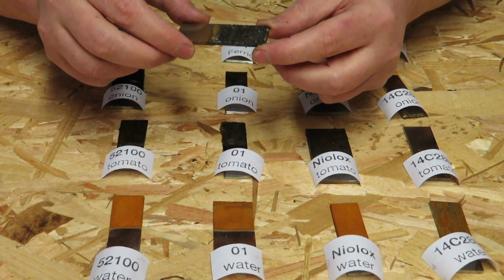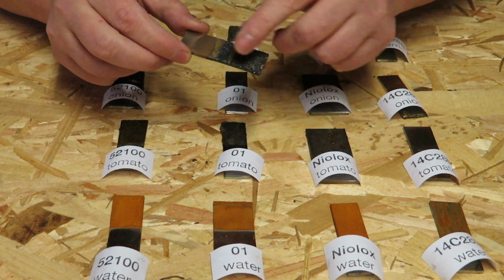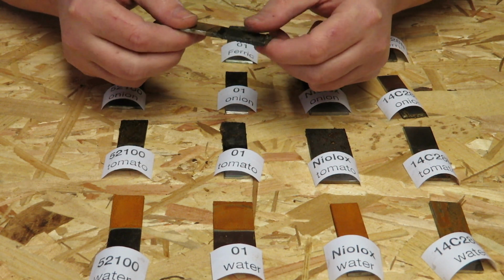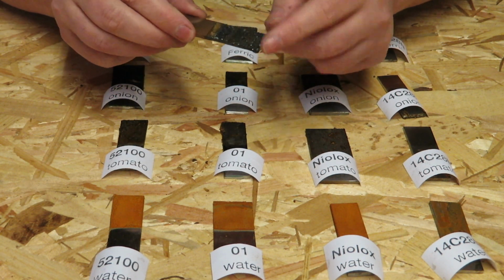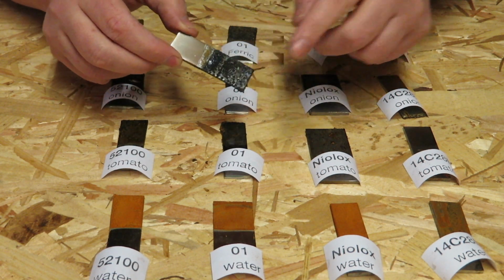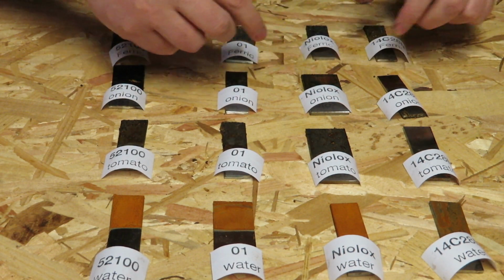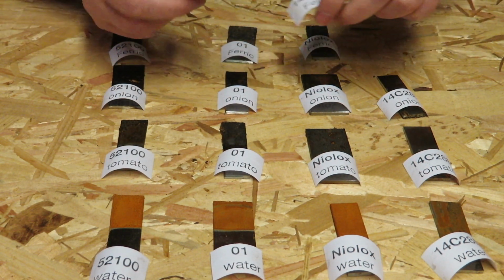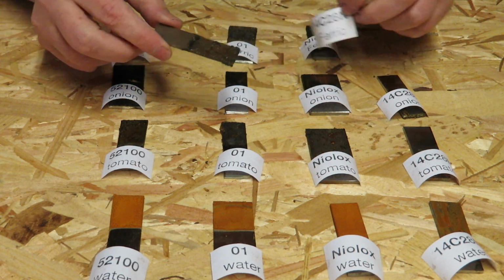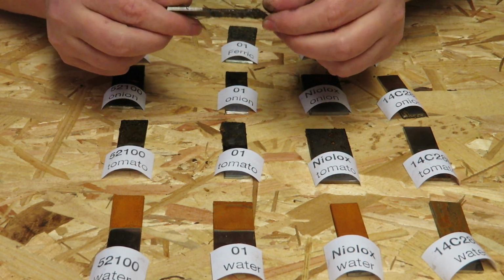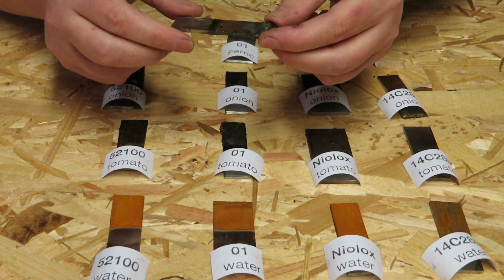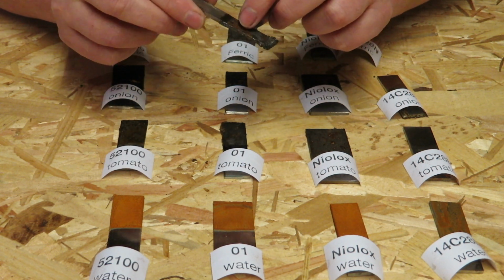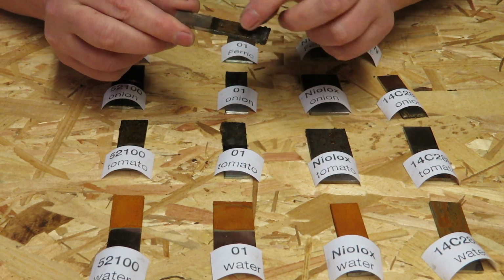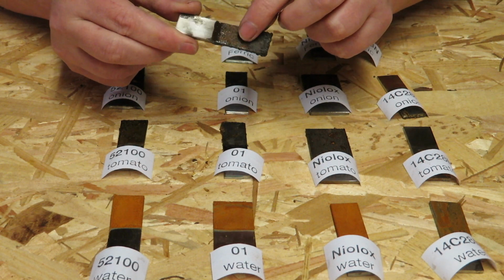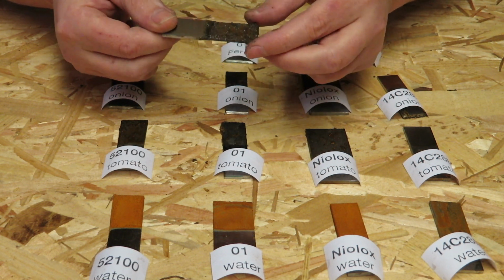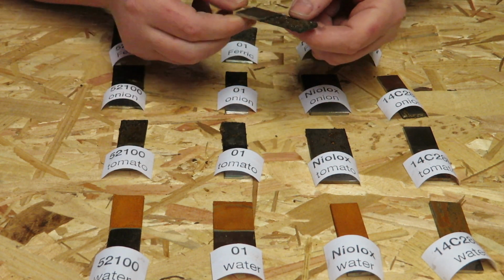The Niolox, very similar to the 01 actually. There was crystals appearing on the top, and it's definitely sort of bitten into that steel. That's not coming off with a paper towel. And then we've got the stainless, which is the 14C28N. And again, that really has bitten into there, and we can start to see those sort of oxidization colours, those sort of reds and yellows appearing slightly on there. And this was the stainless 14C28N.